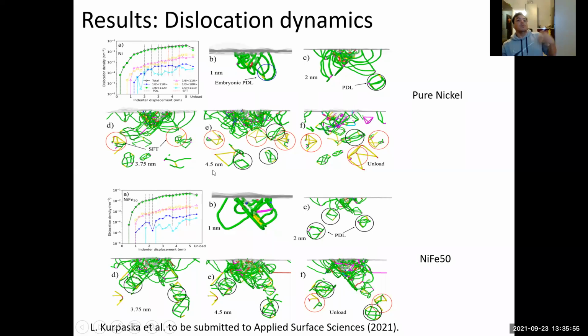So what is happening when you are adding iron? Well, when you are adding 50% of iron, now the mobility of these defects is slower because of the presence of iron. And at 1 nanometer there is no embryonic prismatic dislocation loop, but then there are 2 prismatic dislocation loops already formed, but they go deeper really slowly, so that even the pyramidal shape stacking fault tetrahedron is not formed at 4.5 nanometers, and here for nickel already you have 2, and then you are doing the unloading process and there is nothing.